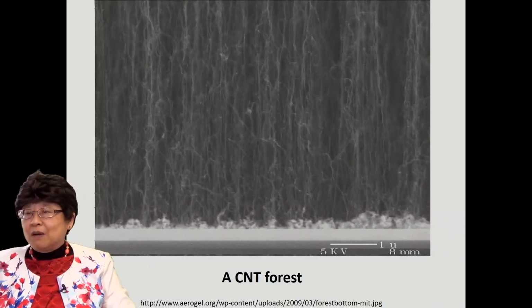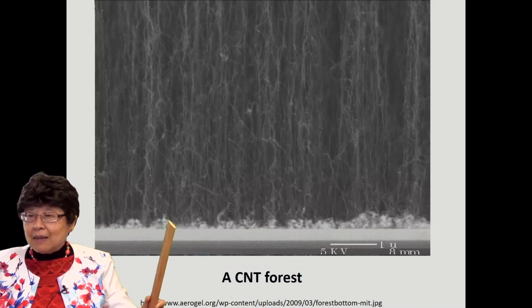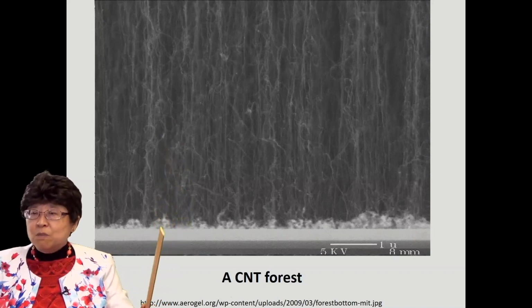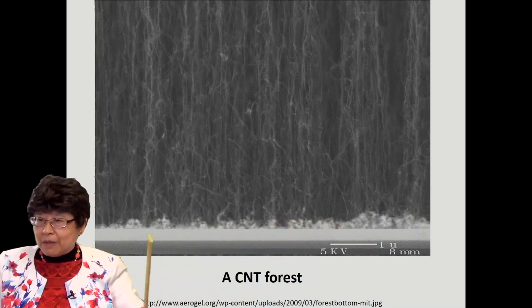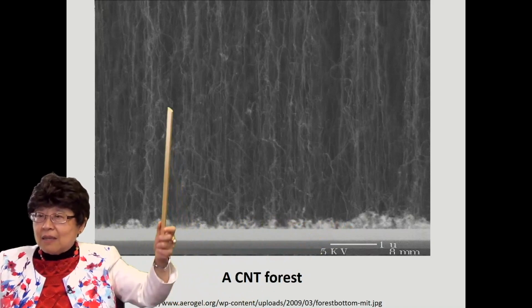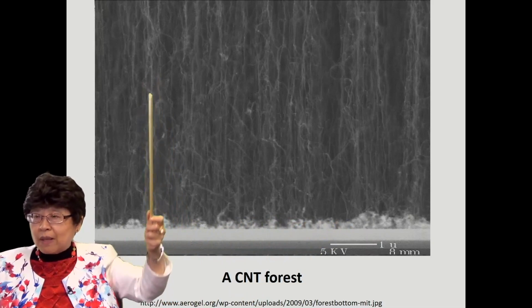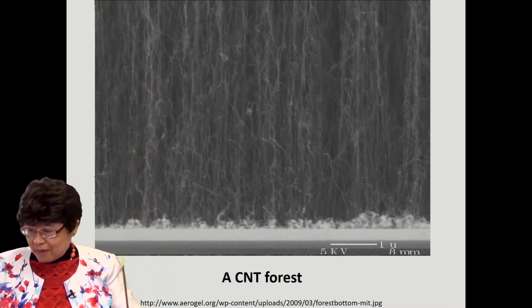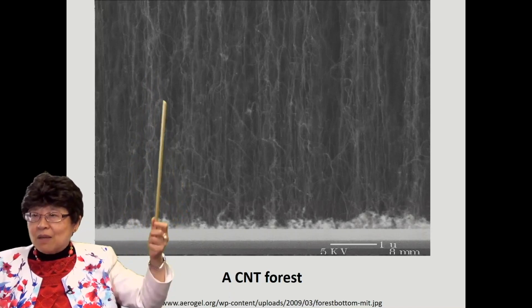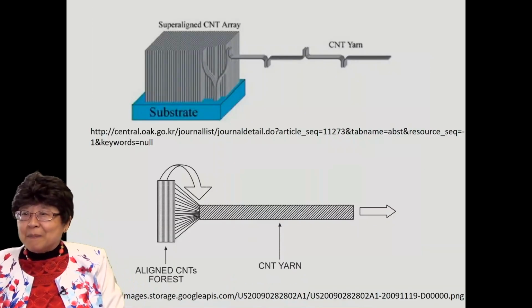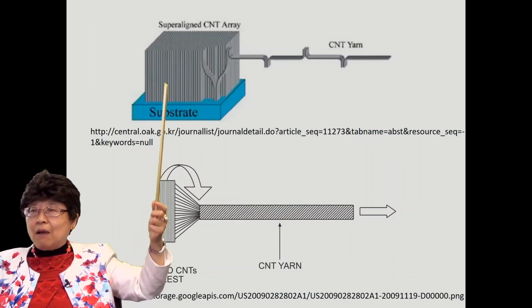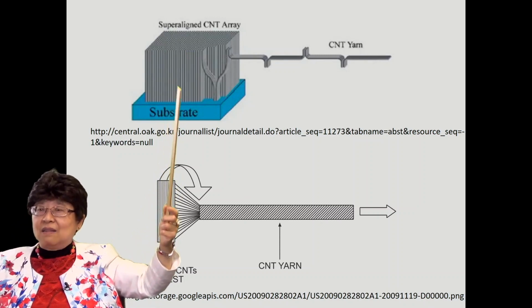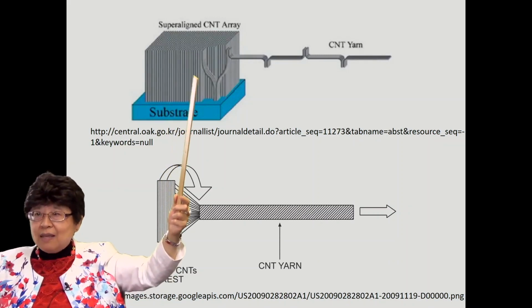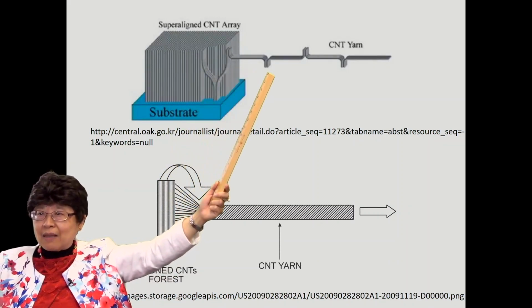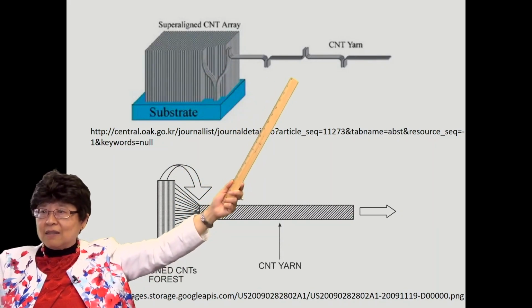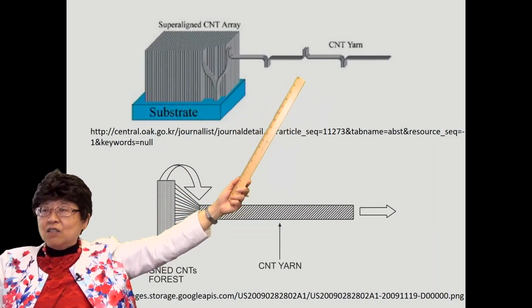Here is another form of carbon nanotube, and that is called a forest, which means that you have catalysts at the bottom here on the substrate, and each catalyst gives you one nanotube growing upward, just like growing hair. And so it looks like a forest. And you can take a very well-aligned carbon nanotube array and pull it like this, and you get a yarn out of it.